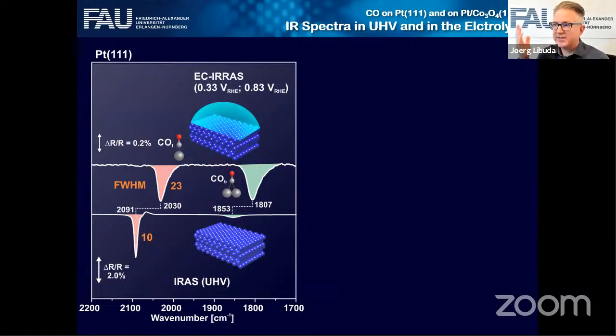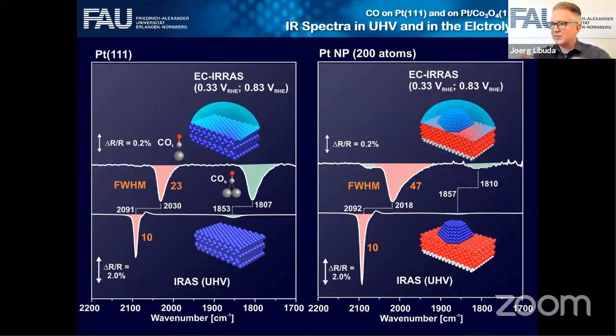Infrared spectroscopy is fascinating, I think, because it allows you to do the same experiment in ultra-high vacuum and in electrolyte. And just as I said again, you can take the same sample, adsorb the same molecule, and then take the spectrum in vacuum and in the presence of the electrolyte. So this is an example for CO on platinum in the electrolyte and in vacuum, and you can see the bridge-bonded and on-top CO. Yeah, and with this transfer of model systems, now you can do exactly the same thing for any model system that you can make in ultra-high vacuum.